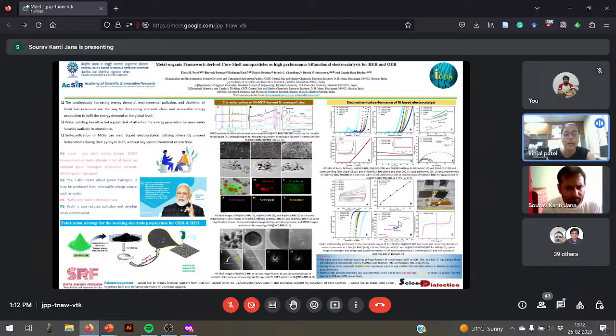As the calcination temperature is increased, the compactness of the structure decreases and the perforated morphology increases, which is observed in the 800-degree catalyst. The HR-TEM image shows that the percentage conversion of the organic moiety into graphitic carbon is highest in the 800 catalyst. The EDX mapping shows that the nickel nanoparticles along with all the heteroatoms are well distributed throughout